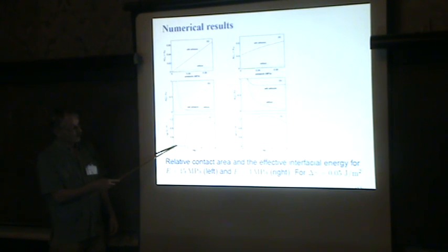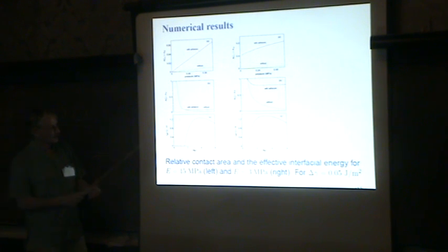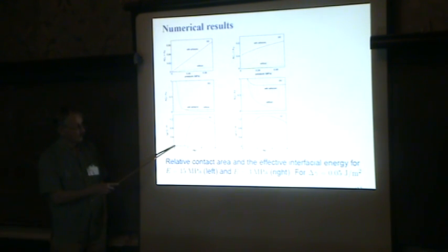So in this particular experiment, if you remove the rubber ball, you don't feel any attraction at all. Our formula predicts zero adhesion force. In this case, adhesion only manifests itself as an increase in the contact area when you look at the system at large magnification. Here is the area at the highest magnification.